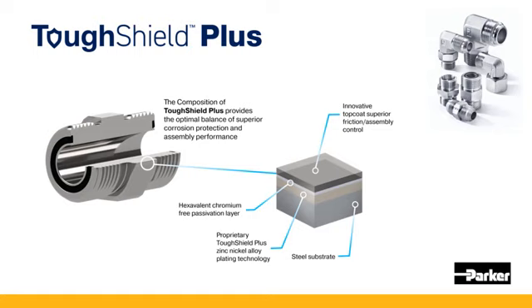First of all, we're starting with a better foot forward. As you already have heard, zinc-nickel is significantly better than zinc. But Toughshield Plus is actually a proprietary zinc-nickel alloy, as well as processing methodology that we've been working on for years. So the advanced plating structure, as well as application or processing methodologies, is really protected under IP, but in a nutshell, it protects the base metal significantly longer than zinc or commercially available zinc-nickel plating systems. So that's the base layer, protecting that steel substrate.